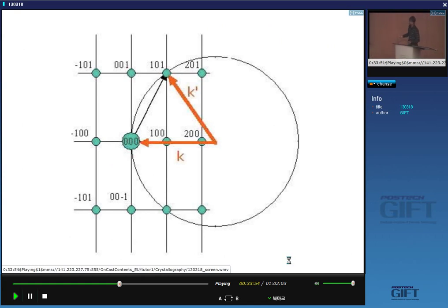Right, so here now I've got that sphere which we call the Ewald sphere. It's got a radius which is 1 upon lambda, superimposed on the reciprocal lattice section here. And this is the origin of the reciprocal lattice. This is the direction of the incident beam, the direction of the diffracted beam. And if the vector k dashed ends on a reciprocal lattice point, then this is the set of planes which satisfy the Bragg condition. This would not satisfy the Bragg condition. So by putting this Ewald sphere onto my reciprocal lattice section, I can identify which planes are going to give me diffraction. Yeah. So we proved that the Bragg law is satisfied when k dashed touches a reciprocal lattice point. This would not satisfy the Bragg condition, this would, and so on. Okay?